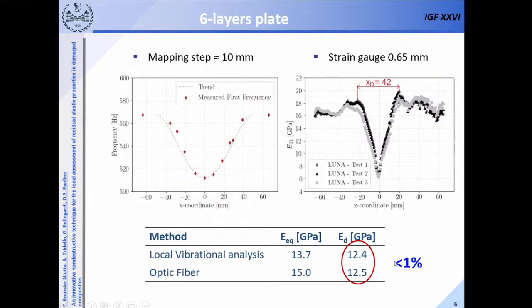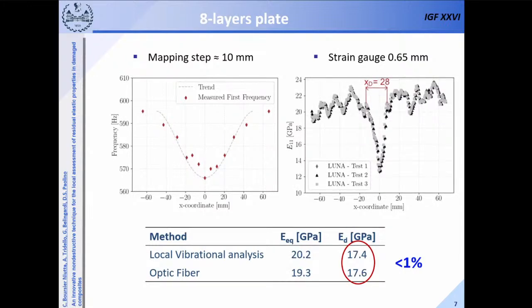And the same conclusion can be drawn also for the 8-layer plate, where again, the reduction of the frequency is proportional to the participation of the damage to the mode shape. And again, the reduction of the elastic properties is clearly consistent. And again, the discrepancy is very, very limited, which validates the technique. And that's it from my side.